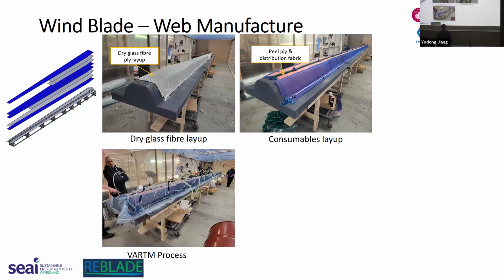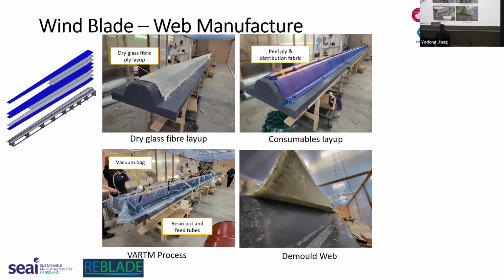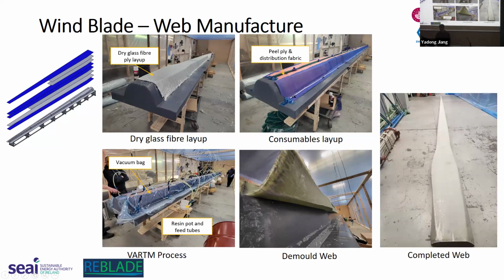Next we have the VARTM process. That's the exact same as you saw in the previous slide. The resin just penetrates so that it changes color. And then the vacuum bag and obviously resin pots, feed tubes are ready to go. And then once it's completed, we rip off all the consumables and the vacuum bags and we demold it. So you can see that's a bit of a sharp angle there. It's kind of looking up underneath to see that sharp edge. And that's basically the flange that we're going to use to bond it to the spar caps. And then that's a completed web.